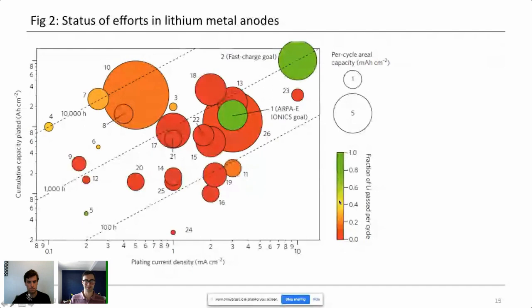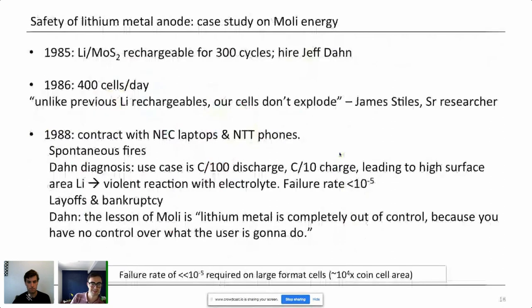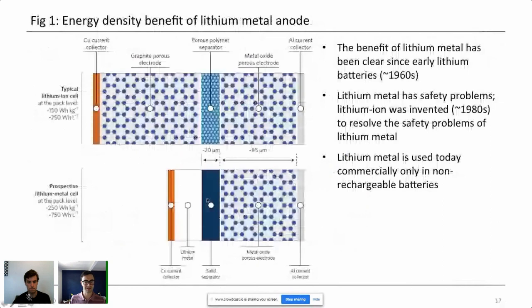Then the color reflects how much excess lithium there is in the cell. So excess lithium is something we haven't talked about yet. If I go back to this figure, what is shown here is only the amount of lithium that's required to cycle the battery. That is, it's matched to the cathode capacity. One crutch that some people use is they supply excess lithium on the anode side. So if you apply excess lithium, you could basically just imagine this layer growing. At some point, if you're using a lot of excess lithium, then you've completely diluted any benefit of removing the graphite and switching to lithium, because at roughly 200% excess lithium, the anode is exactly as large as the graphite anode is, and there's then no energy density benefit in switching from graphite to lithium.